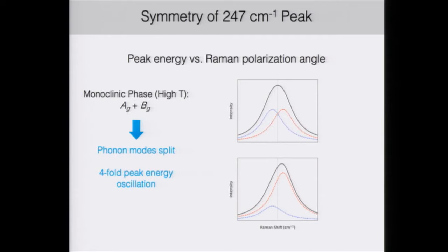However, in the monoclinic phase, these phonon modes are actually split slightly in energy, and therefore, as you modulate the Raman polarization angle, the relative intensities will change, and thus the overall peak that you see will actually be shifting slightly in energy. And so you can work out using Raman tensors that this will give you a 4-fold peak energy oscillation as you sweep the polarization angle from 0 to 360 degrees.